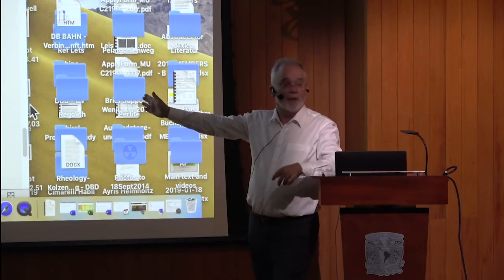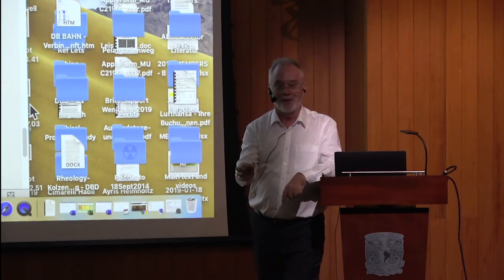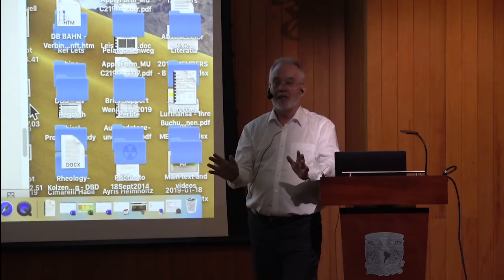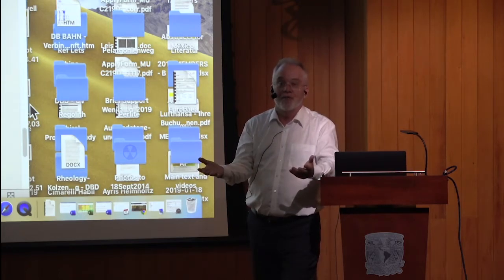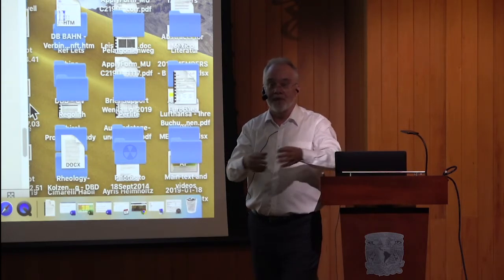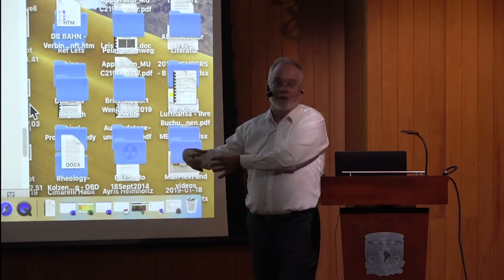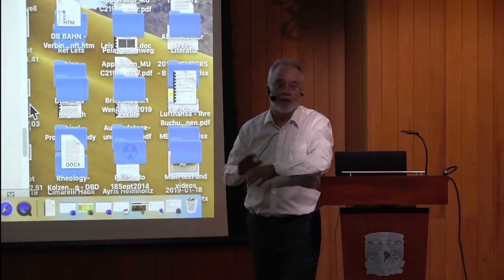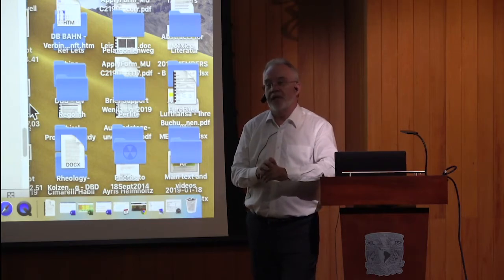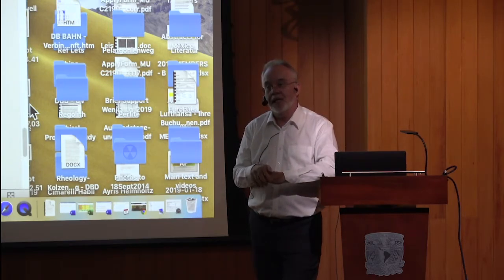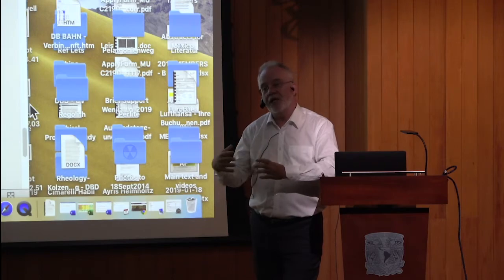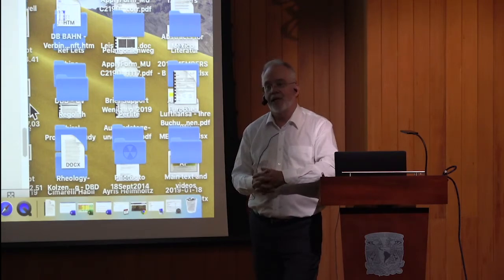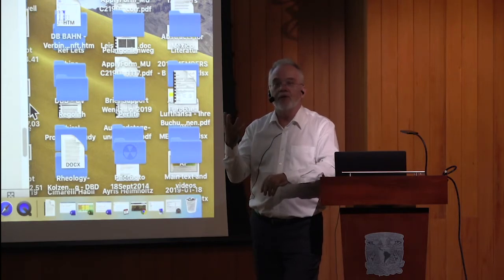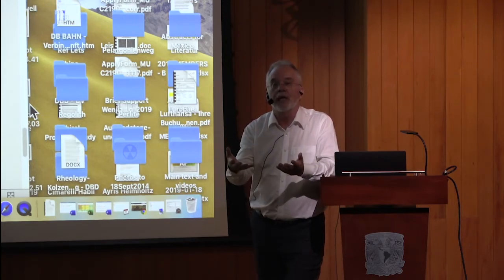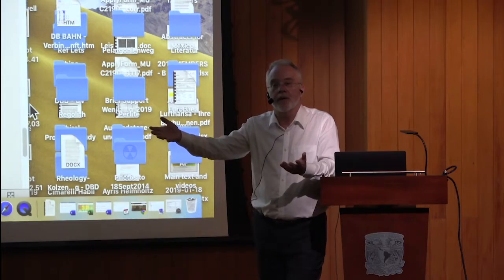And it does make a difference in detail for, of course, the largest part. The largest pyroclasts we get are the diameter of the sample. This is clear. So it unquestionably makes a difference, for example, in our grain size distribution if we double the size of the experiment, because we get particles on the coarse end which are twice as large in diameter. So there's no question in the simplest of analysis that it makes a difference in detail. But we think that we can scale these distortions in grain size variation according to the size of the fragmenting system. I mean, ultimately, we want to go out in the field, look at the particles, and see if they look like our experimental particles.